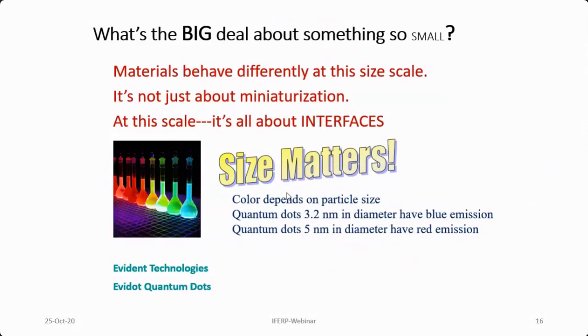So what is the big deal about something so small? As we know, size matters. Here is an example from a company called Evident Technologies, which made quantum dots and marketed them as Evidot quantum dots, around 12-15 years back. They made quantum dots of size between 3.2 and 5 nanometer, and as size increases, the emission of these quantum dots changes color. The smallest size quantum dot gives blue emission, while at 5 nanometer it gives red emission. So you see the size-dependent optical properties of nanomaterials, which can be exploited for very many things. Quantum dot based display devices are already coming into the market.